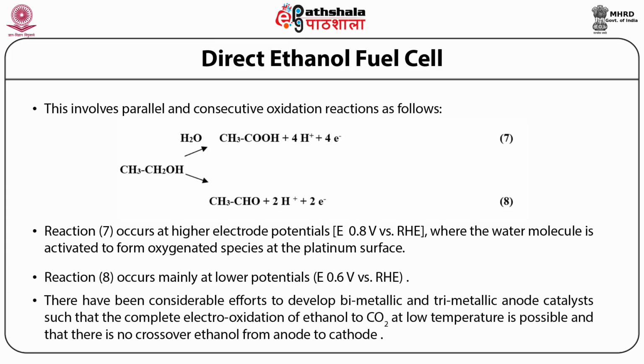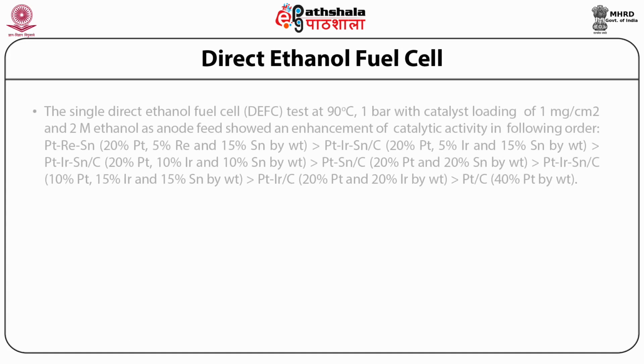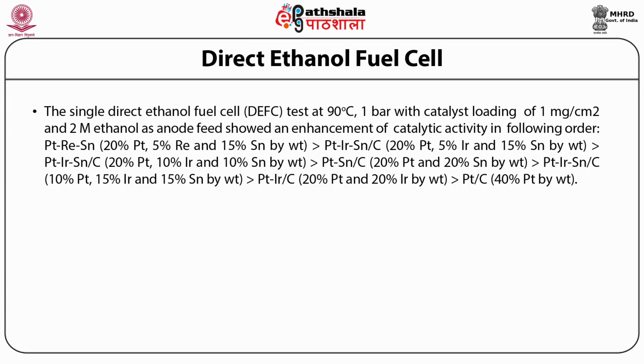There have been considerable efforts to develop bimetallic and trimetallic anode catalysts such that the complete electrooxidation of ethanol to CO2 at lower temperature is possible, and that there is no crossover of ethanol from anode to cathode. A single DEFC tested at 90 degrees Celsius, 1 bar, with catalyst loading of 1 mg per centimeter square and 2 M ethanol as anode feed